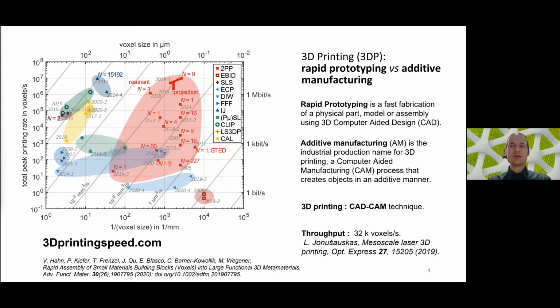And as we might see, there are some very precise technologies like e-beam, electron beam lithography, which are pretty slow, or some liquid-based ones like inkjet printing techniques, which can be very fast, but not very high in resolution. So they are not offering high precision. And of course, there is a third dimension, like material. It depends on what materials we can process using one or another tool. And two-photon polymerization, the technique I'm presenting here today, takes a good place in the sense that it covers both resolution and printing speed. And we are very happy to be in the top 3 using a single beam approach, which enables high flexibility.